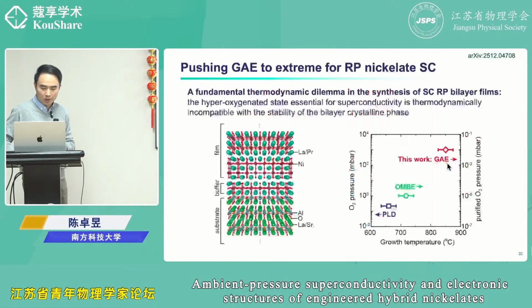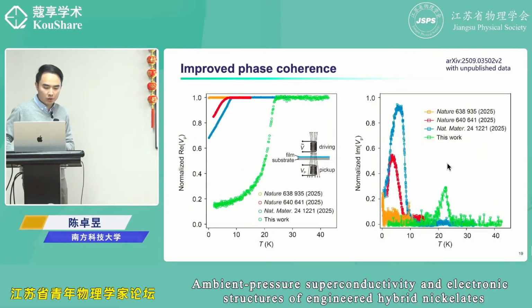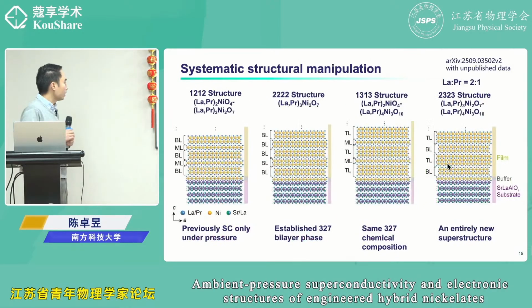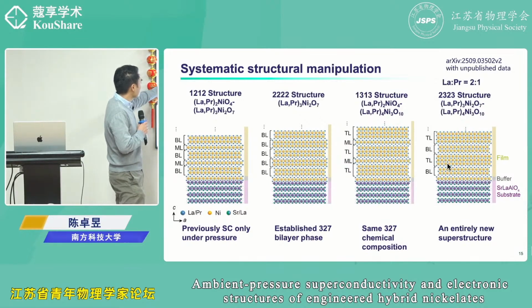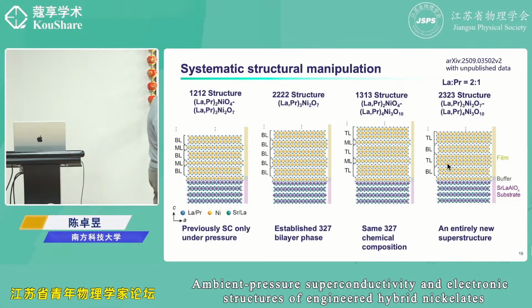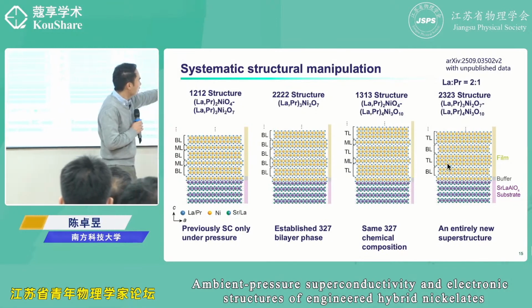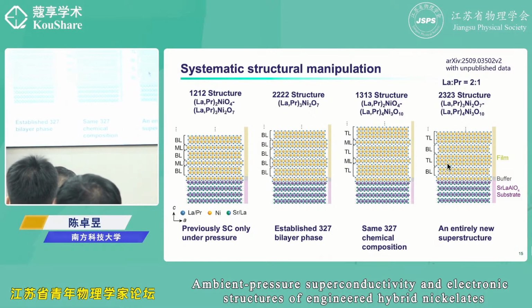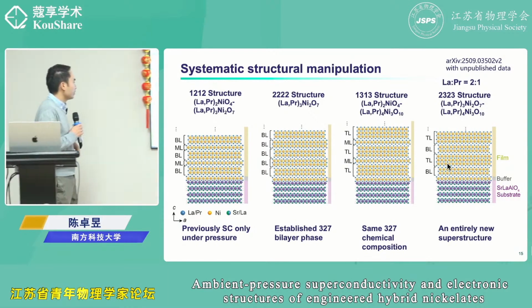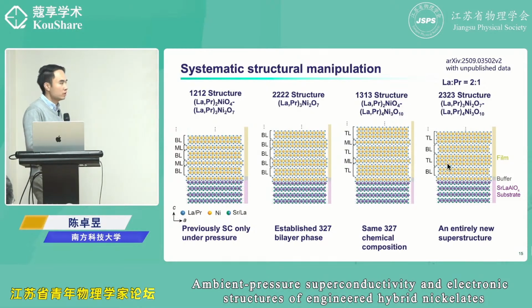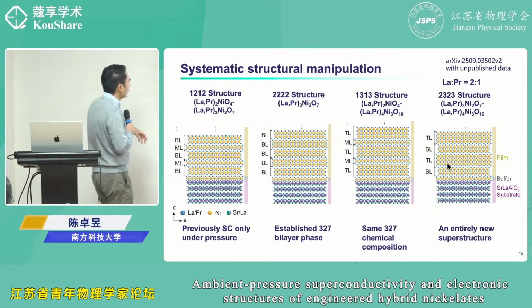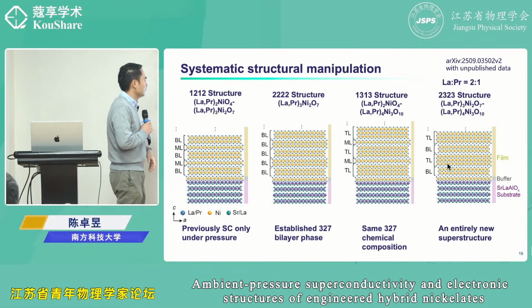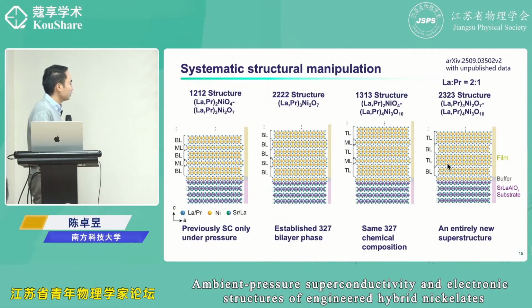Yes, in that case we also use this method. So this is the buffer, the reconstructed interface. It's all the same. For this buffer, we think it's inert. It's pretty insulating. We measured it's completely insulating, so it's just for structural purposes. It's not affecting the superconducting property above.